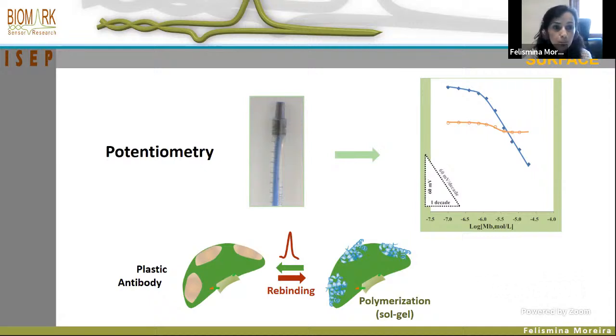Then the beads were incorporated in one PVC membrane and drop casted on this kind of electrode, a syringe electrode. It's very simple. We have one syringe, one copper wire, and carbon ink as a conductive material to construct the electrode. The membrane was drop casted on top of this layer. The detection was performed by potentiometric technique, and we measured the potential against different concentrations of the protein, in this case myoglobin.